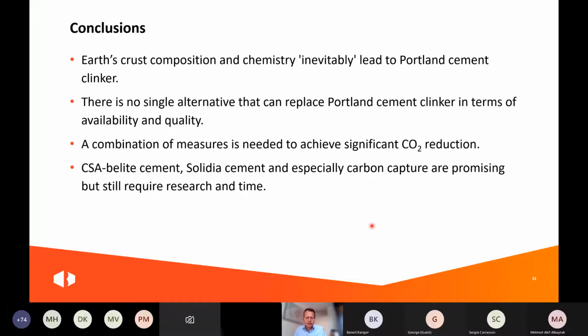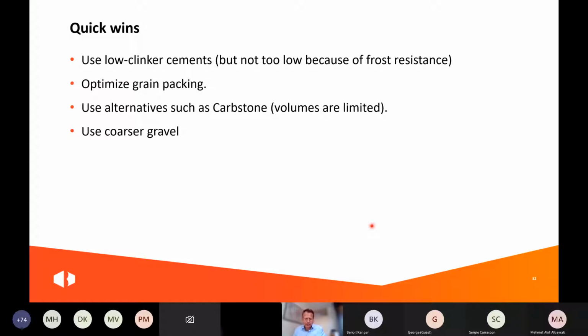So we need a lot of different measures to reach a significant CO2 reduction. And in my view, this calcium sulfur-aluminate belite cement, Solidia cement, but especially carbon capture are promising to help in this net CO2 target. But we need time, that's for sure, especially for carbon capture, despite already one plant being adapted on a large scale. It will need 10 years or more before we will see it on a larger scale. So that's unfortunately on a short-term availabilities to reduce CO2 are limited.